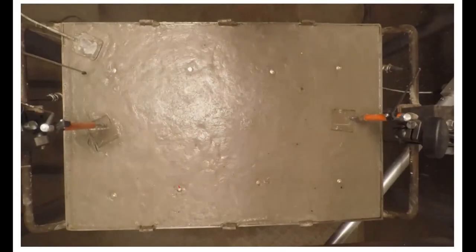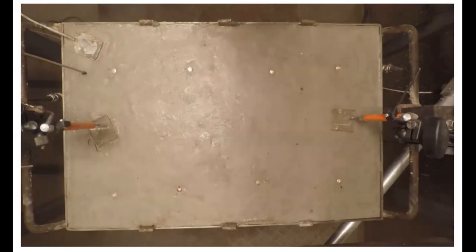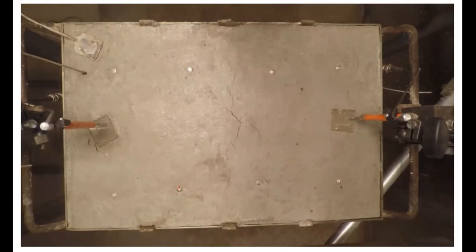Initially, there was a water layer and it evaporated. And now the surface is very dried. With time, you will be able to see some crack formation on the surface of this concrete, which is much similar to how a lot of ladies utilize moisturizing cream to protect their skin. It is much similar for concrete as well. If the evaporation is higher than the bleeding, then there will be a risk of this kind of crack formation. We call it plastic shrinkage cracking.